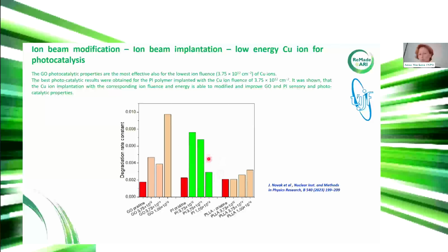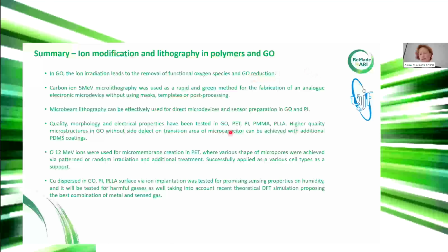When we put the active surface into this solution, we follow the absorption spectra of the solution to see how the organic dye is decomposed in time. So in our case, it seems very prospective to use low fluences and to use polyimide and graphene oxide.